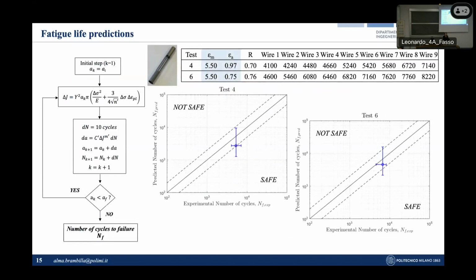So here we have the results for 2 of the tested conditions, where the experimental number of cycles to failure obtained for the 9 wires of each sample on the x-axis is compared with the predicted number of cycles to failure on the y-axis. Here the vertical scatter band in the prediction is obtained by assuming an initial defect size equal to the mean value of the defect distribution and the 95th and 5th percentile values of the distribution. A perfect match between the predicted number of cycles and the experimental number of cycles is obtained in correspondence of the solid line, while conservative predictions are obtained below it.